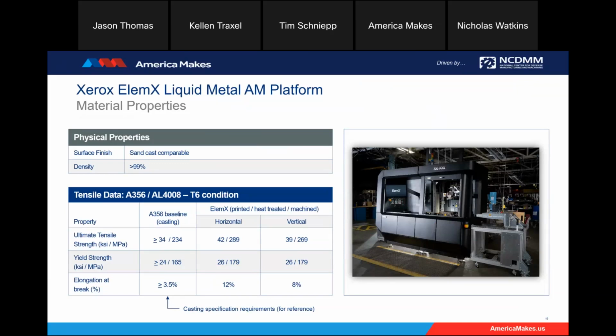And then the bottom table shows basic mechanical performance after the T6 heat treatment that I mentioned. So that's a printed block that is then heat treated to the T6 condition and the specimens are machined. In the first column of that table is the specification requirements for casting. A356 has the same composition as the 4008 series alloy that we offer.